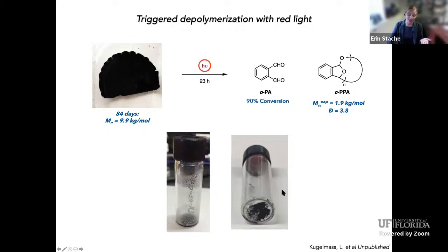But the question is, can we still trigger depolymerization when we want to? And so we took this film that had been sitting on the windowsill for almost 3 months, hit it with red light, and we get clean conversion to monomer with a little bit of oligomer left over. You can see down here, this is the experiment that Liat ran, where the monomer has collected on the glass as it depolymerized, and there's just a little bit of aggregated carbon black and polymer left in the bottom that wasn't getting hit with light anymore.